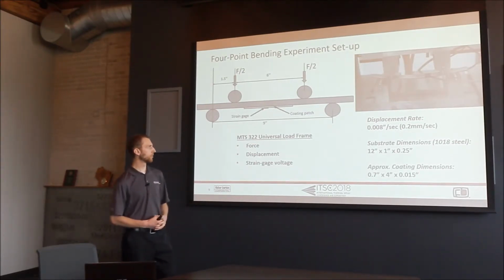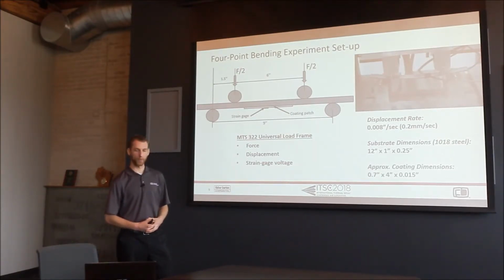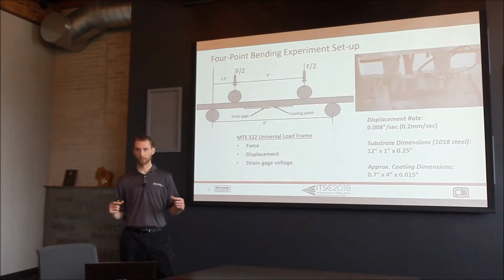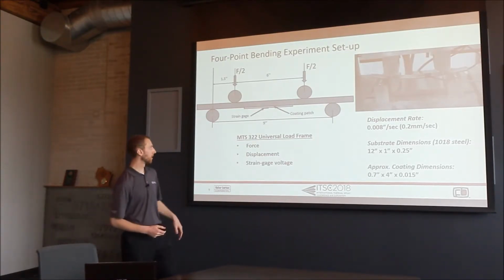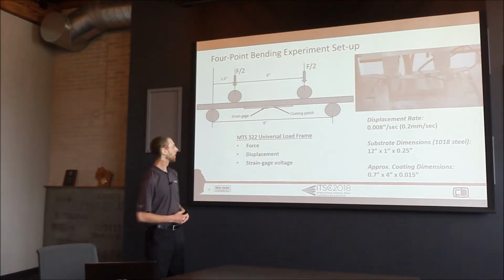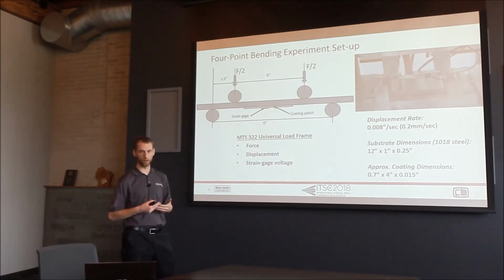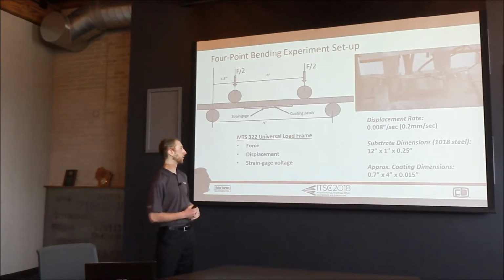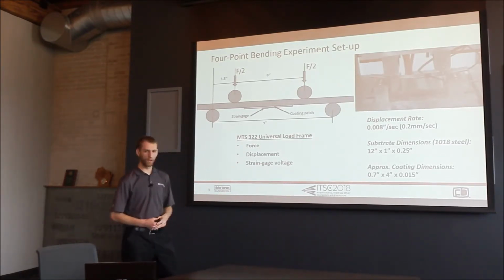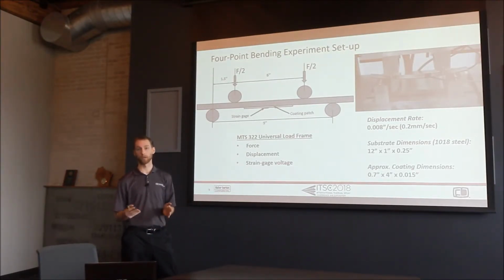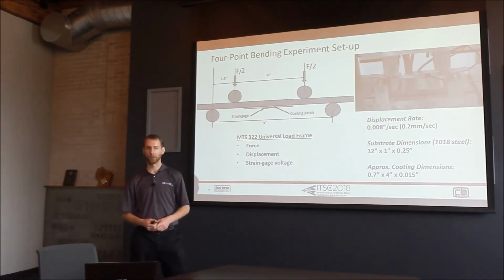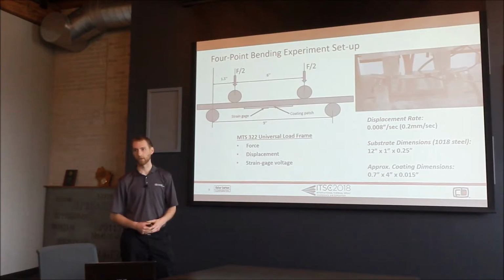So, fairly simple geometry. We have a 12-inch by 1-inch by 1/4-inch 1018 steel substrate, and then we apply the coating on the bottom side, on one side of the bar, to put the coating under tension. As the force pushes down, that's putting the coating under tension. And then we have a strain gauge that's applied to the surface of the coating. The strain gauge is how we truly understand if there is still adhesion or if at some point we've lost adhesion. But we'll also see that the strain gauge can allow for other behavior to be understood at the same time.